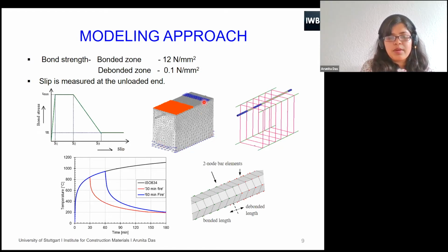So this is the top uplift. This is the restraint which is there to prevent the uplift, and these are there to prevent the sliding, and this is there to keep the specimen in position. The specimens are being pulled at the front end, and slip is measured at the rear end, and this is the heat. Basically, this is the fire. This is the portion where fire is applied.